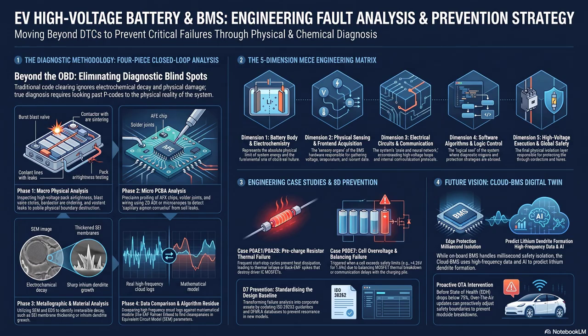It's terrible. If you continue to abuse the battery, these spikes will grow longer and longer until they eventually pierce right through the ultra-thin plastic separator membrane that physically divides the positive and negative sides of the battery cell. And if they pierce that separator, you get an internal micro short circuit. The positive and negative sides are now physically connected by a wire of pure lithium. The battery just shorts itself out. The battery begins bleeding its own energy internally, dumping all that stored power into a tiny, localized point, creating massive, intense heat. Which causes a fire. This localized heat boils the electrolyte, generates gas, and often triggers catastrophic thermal runaway.